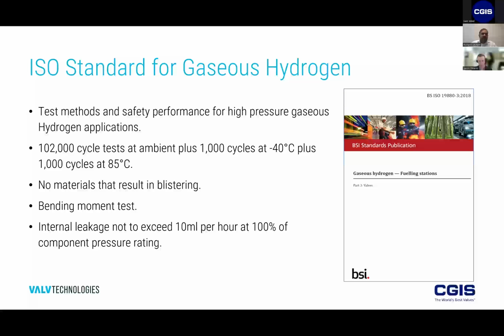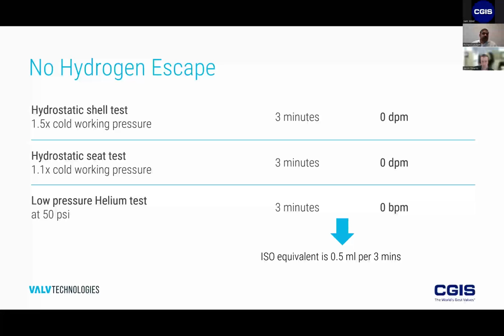And I think that we won't see any true zero leakage standards coming out. Part of the reason for that is even if you just took a piece of pipe and shut it off on both ends and pressurized it with hydrogen up to 10 or even 15,000, over time, that hydrogen will seep through that piece of pipe. Even though in valve design there are, I guess, more chances for escape, whether it's leaking by between the seat and the ball, or through the fugitive emissions, even in a piece of pipe there still is going to be some rate of leakage, probably not very much, and not to the extent where it's going to be dangerous. But that's why we foresee that there won't be any zero leakage standards, but there will be an acceptable range of standards that everyone will hopefully finally agree on.